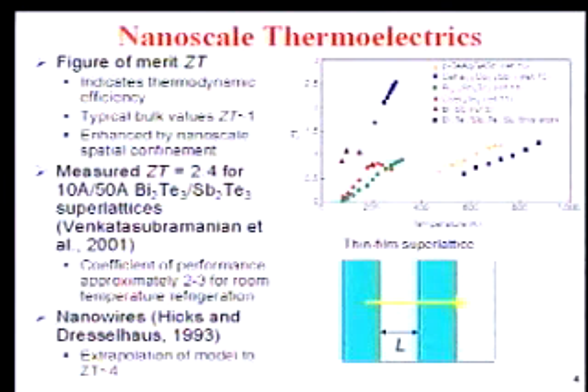Some recent work by a group at Research Triangle Institute has shown that we can use nanoscale structures to significantly improve thermoelectric performance. And so we see in this graph that in using different materials, and this is mostly historic materials, taking these superlattice materials of 10 angstrom and 50 angstrom layers of traditional semiconductor materials, they can achieve a ZT of 2.4. Now, if you don't know what ZT is, I'm not going to explain it to you, but it's a figure of merit that takes efficiency out of the equation. You can convert it to an efficiency, and I'll talk about that.